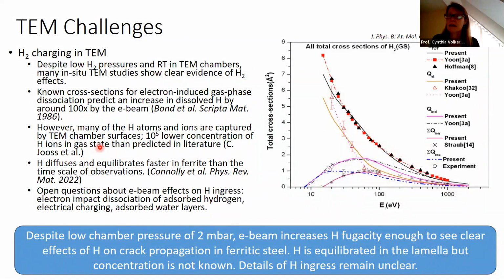However, we know from studies at the University of Göttingen that the hydrogen atoms and ions that are created by the electron beam are captured almost immediately on the TEM chamber surfaces. And the result is that the concentration of hydrogen ions in the gas state is 10 to the 5 times lower than predicted based upon those known cross sections. So this idea that we're simply producing a plasma of hydrogen atoms or ions in the chamber with the electron beam, and that this raises the effective partial pressure, dissociation is no longer necessary on the surface, and as a result, one argues you increase the amount of dissolved hydrogen. There seems to be some problems with this argument.